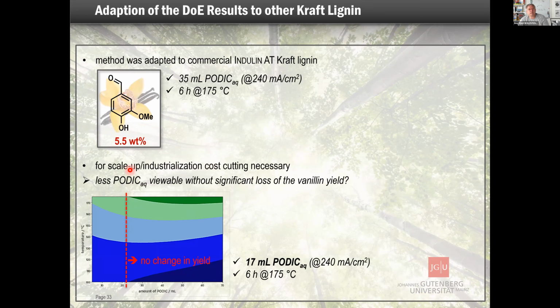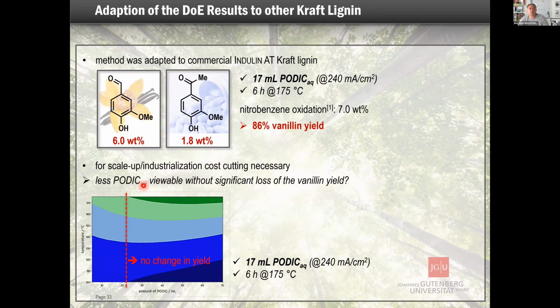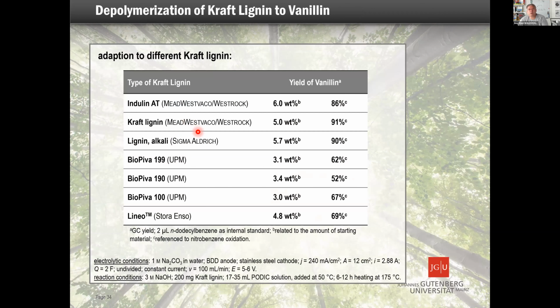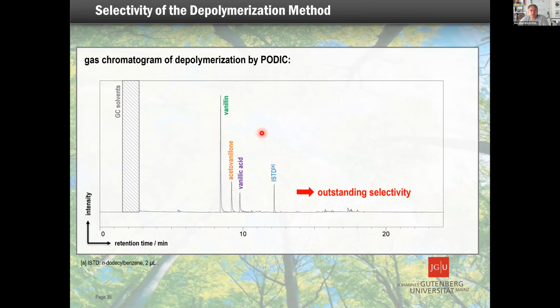The important thing is that you just have to make PODIC, and this only works at boron-doped diamond. But in the optimized version, you see we still have 6 weight % with 1.8 weight % of acetovanillone. If you compare this, then you're in a different range than before. And this is, at the moment, I think, one of the best results from commercially available kraft lignins. If you look at the product mixture, if you work on a larger scale, you have vanillin, you have acetovanillone, and a little bit of vanillic acid, but the selectivity is quite outstanding compared to other methods.